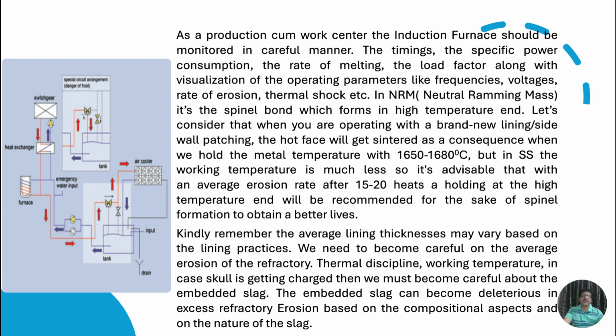But in SS, the working temperature is much less, so it's advisable that with an average erosion rate, after 15 to 20 heats, holding at the high temperature end will be recommended for the sake of spinel formation to obtain a better life. Kindly remember the average lining thicknesses may vary based on erosion of the refractory.